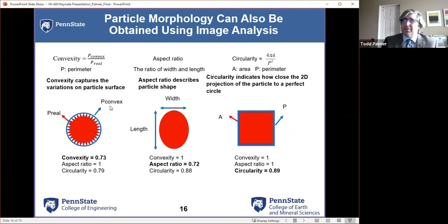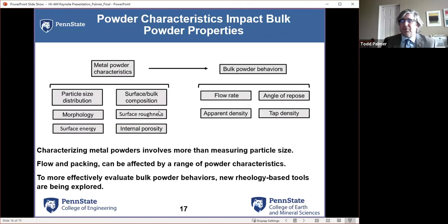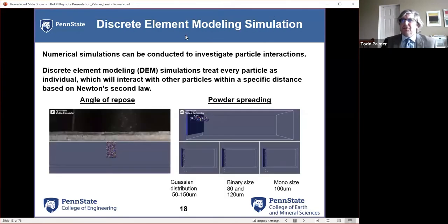So that lets us start to think of particle morphology. Convexity is one, and this is basically variations on the particle surface. Aspect ratio tells us how close it is really to a circle, and circularity is how close that 2D projection can fit a perfect circle. So you start looking at some of these, you can get some wide variations in particle morphology. Now, particle size and morphology are only a couple of things. That gives us the particle size distribution and the morphology, but there's a lot more that goes into these bulk powder behaviors that we're talking about. We know flow rate, angle of repose, all of these general things, but there are things within the powders that are going on too. And that's where some of these newer tools are coming in.